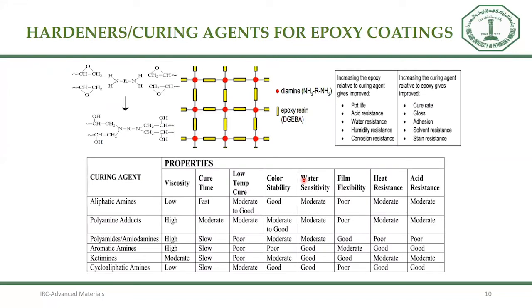Hardeners play a major role in improving or altering the properties of the resultant epoxy coatings. For example, when you consider aliphatic, aromatic and cycloaliphatic amines, depending on the property we need, we can select a different kind of curing agent. For example, when you want really high resistance toward heat and acid, we can select aromatic amines or cycloaliphatic amines. So what I'm trying to tell you is that depending on the end user application, we can select different kinds of amines.